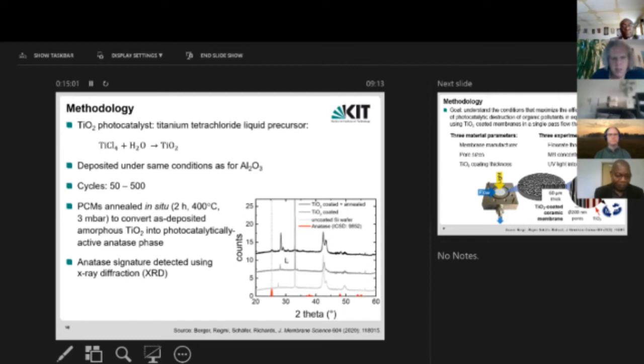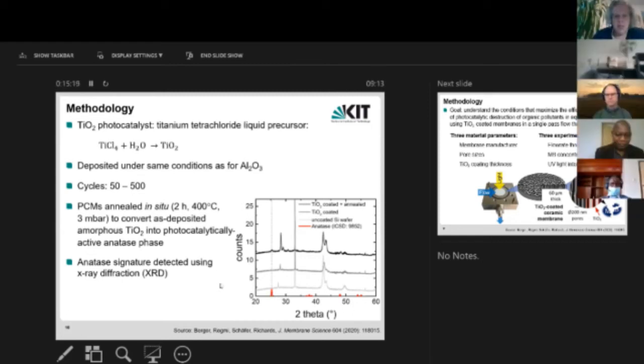And as I've shown on the right, there are some small peaks in the top black XRD diffractogram which line up with the presence of anatase shown in red from the reference database. Not strong because these films are very thin.